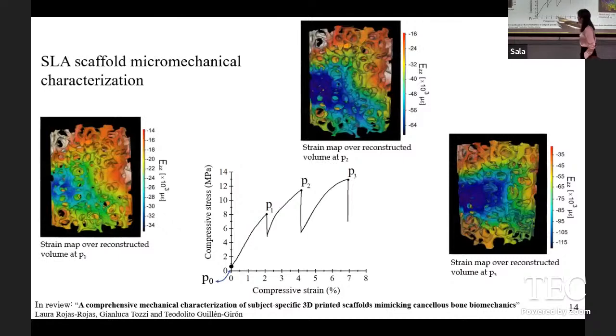And again, we acquired the information at different loading points, and we have the strain map for the SLA scaffold. Again, the strain focuses barely in the middle of the sample, and at least in an inclined plane also. Two main things I want to point out for this result is that the SLA scaffold is very similar to the bone scaffold. That was something that we wanted to achieve.